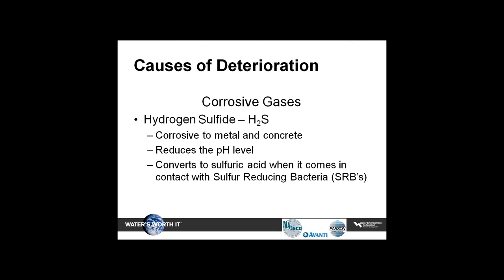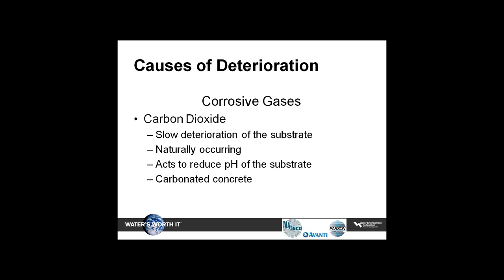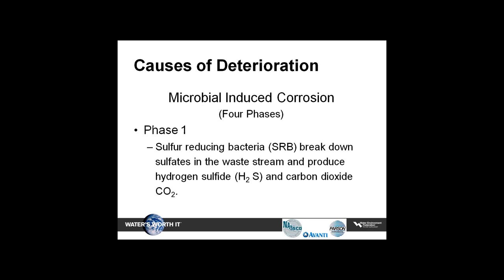Some of the corrosive gases that we come across are obviously hydrogen sulfide. It's corrosive to metal and concrete. It reduces the pH level, and it converts to sulfuric acid when it comes in contact with sulfur-reducing bacteria. Another gas is carbon dioxide. It's a slow deterioration of the substrate. It's naturally occurring, and it acts to reduce the pH of the substrate, and it leads to carbonated concrete.